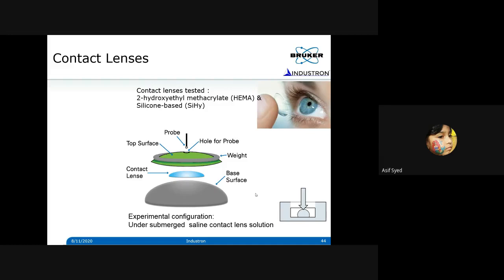And it's very important to understand this part. Basically, hydrogels are mostly water, okay? And it has a content of water as well as a network of structure. So when you apply a stress, this water will squeeze out and come back. So what you're measuring is basically a combination of fluid flow in and out as well as the matrix that it supports. So when you make a measurement, you need to keep in mind it's not a straight elasticity problem, it's a poroelastic problem, and also has some viscoelastic component because the matrix is a viscoelastic material. So it's a combination of both, okay?